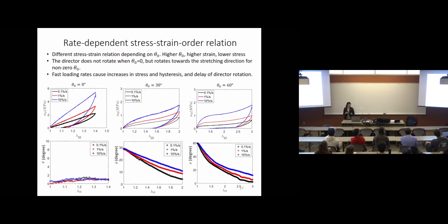Here I'm further showing you some results for different theta angles. The theta naught means the angle of the director in the initial state with respect to the stretching direction. So in the first case, it's essentially parallel to the stretching direction, but in the later cases, it's in a tilted direction with respect to the stretching. As you see, the stress-strain behavior looks very different. That is mainly because for the 0 degree case, the director doesn't rotate at all. But for 30 degrees and 60 degrees, the director can rotate while you increase the external strain. That's why this leads to different stress-strain curves, because the rotation of the director gives rise to a large spontaneous strain. Therefore, with increases of the initial theta angle, you can see a higher strain that you can achieve, and with a lower stress, due to this spontaneous strain.